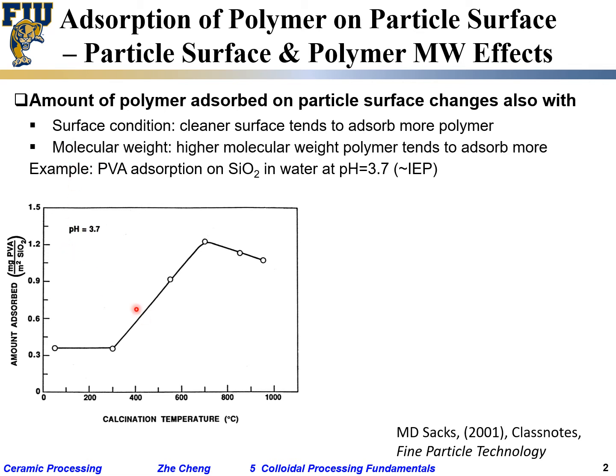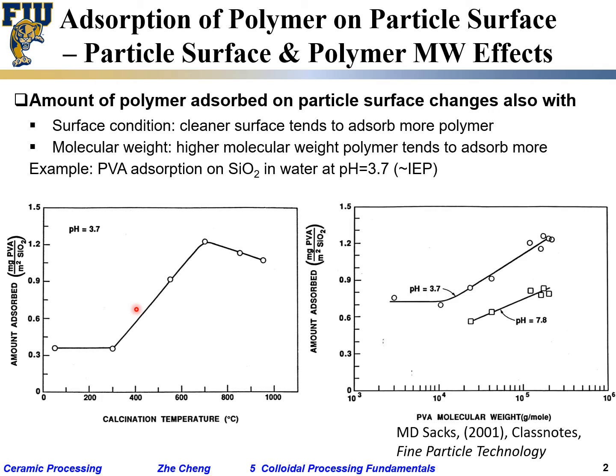Okay. And another one is about molecular weight. Here I'm plotting the same thing, how much polymer adsorbed onto the silicon dioxide surface, but the horizontal axis is PVA polymer molecular weight. And what you find is, for the same pH, I control for the same pH, the higher the molecular weight, the higher the total adsorbed amount, relative amount, for both pH conditions. The higher the molecular weight, the higher the surface coverage. Not by too much, but a slight increase.